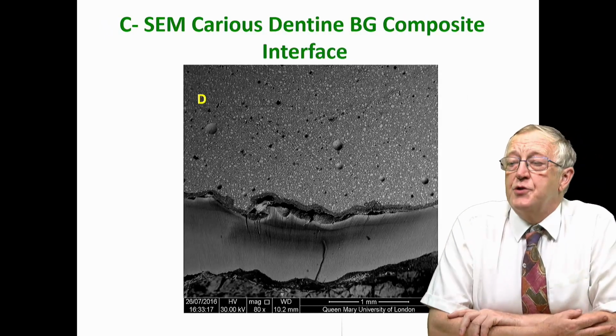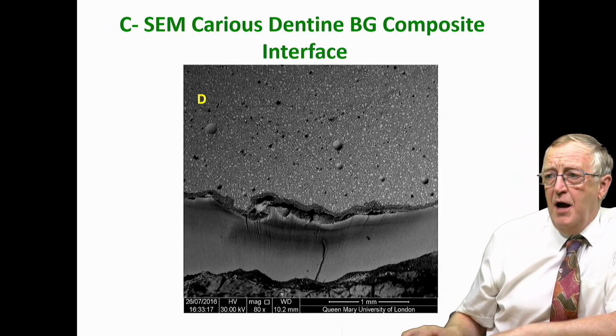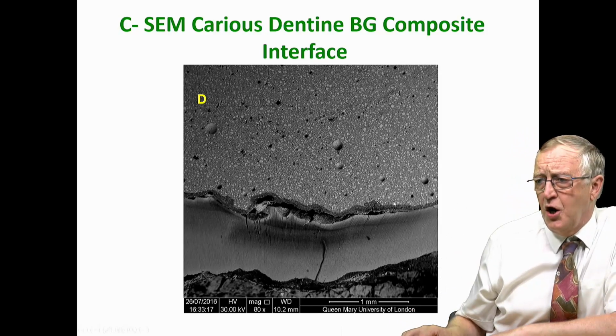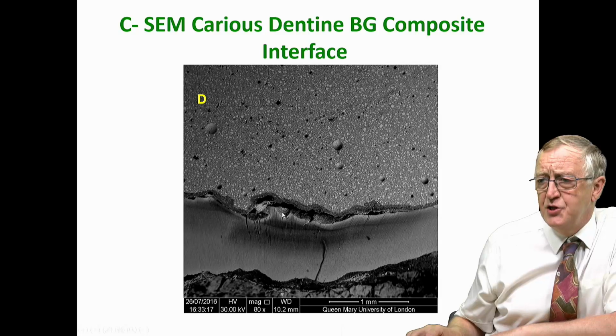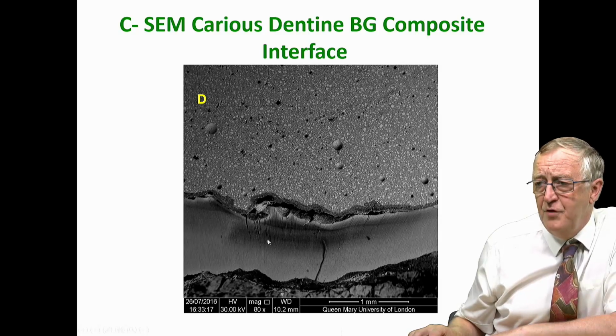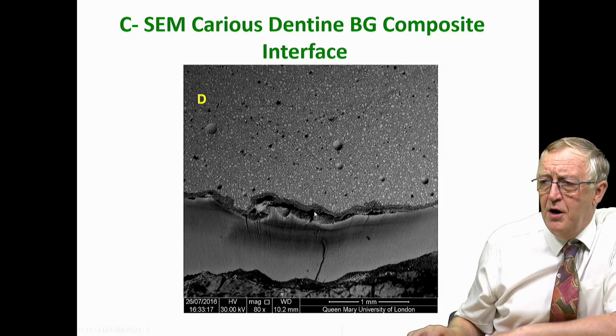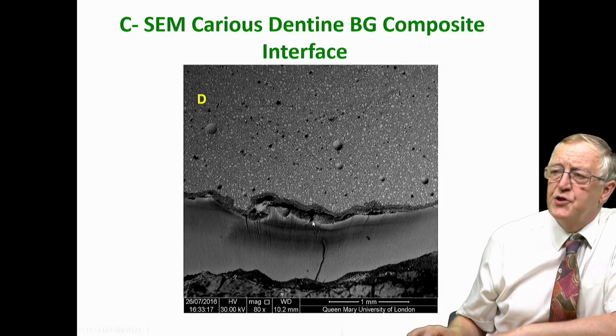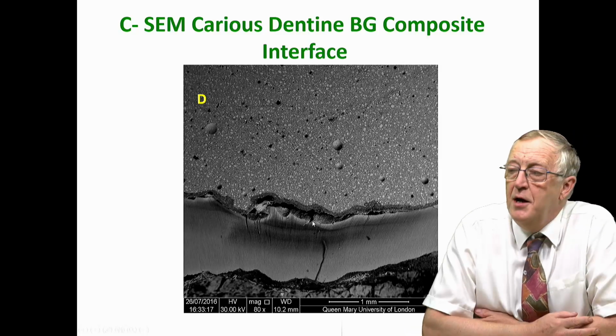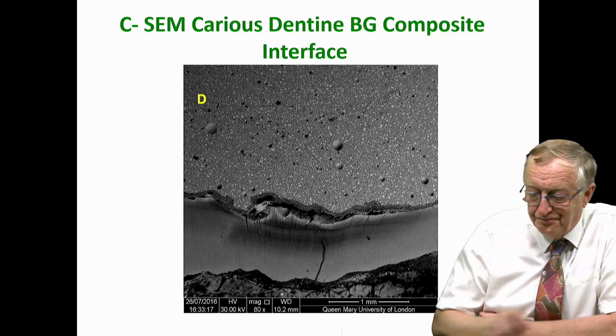This slide shows the base of the cavity, and what you can see is the dark layer in the composite surface where we've lost mineral in this backscattered image. You can see an increased mineral content at the surface of the dentine. You can still see we haven't remineralized the carious lesion completely. And this is a gap that's formed as a result of shrinkage in the SEM because of water loss.